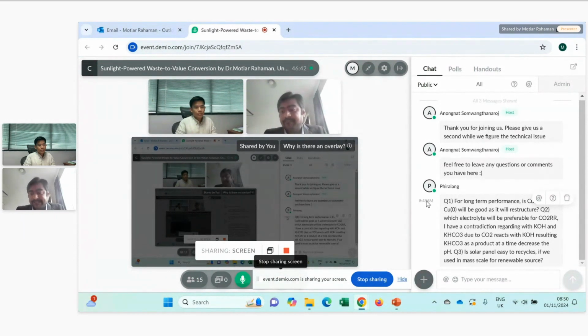For KOH, like basic condition, you have to be careful. If you purge carbon dioxide through potassium hydroxide, it may reduce the pH. It may bring it back to potassium bicarbonate. But KOH is also a very important electrolyte if you want to do some studies at higher pH, especially for gas diffusion electrode flow cell studies, where you can use a flow of KOH with carbon dioxide. That is quite helpful as well.